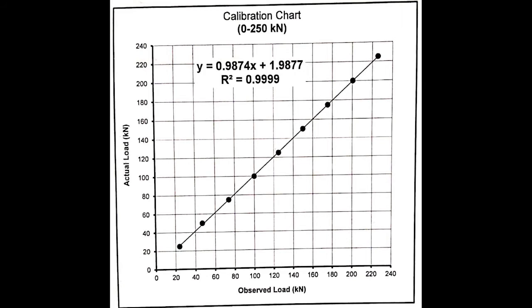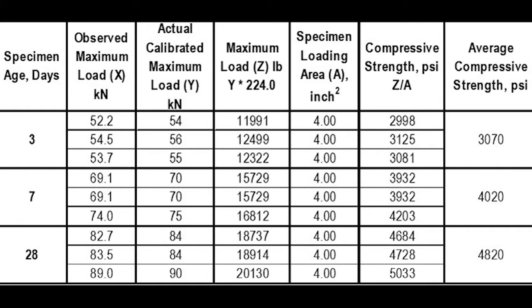We have to convert this observed load to actual load using this calibration equation on the calibration chart. We have to repeat this procedure for the other two cube specimens. Similarly, we will test 3 specimens after 7 days and the other 3 specimens after 28 days. Here in the video, you can see the test results for 3, 7 and 28 days.